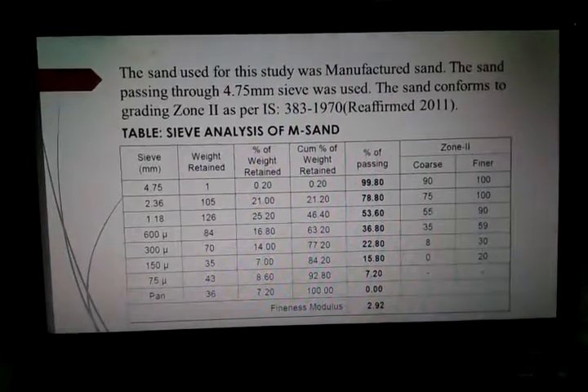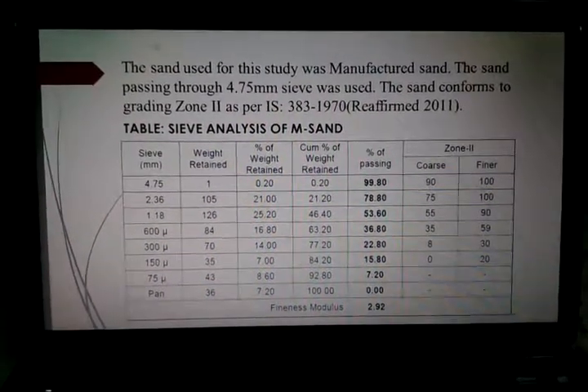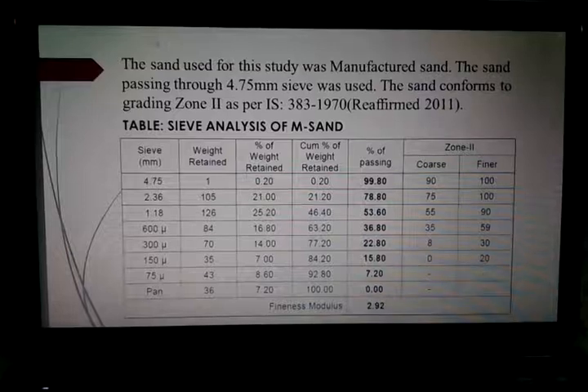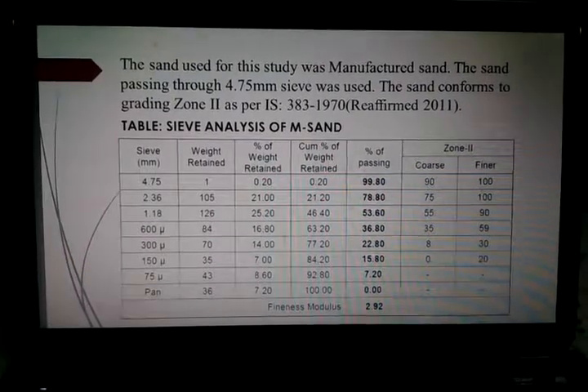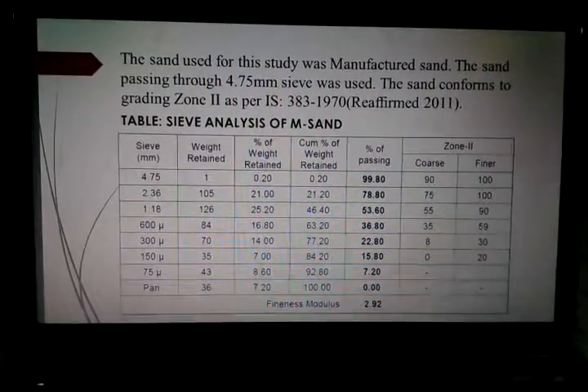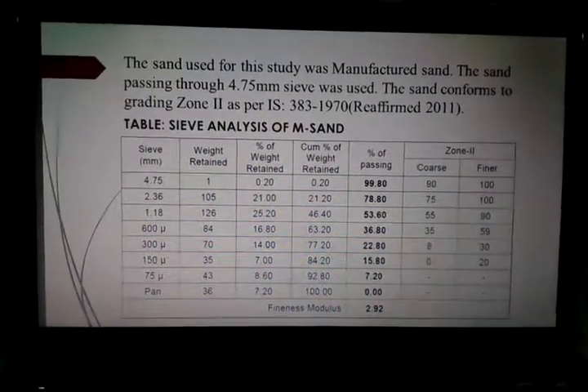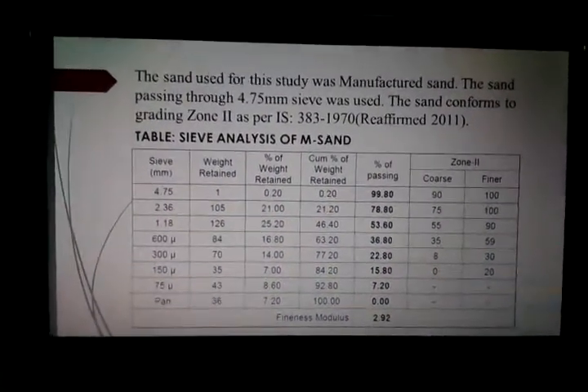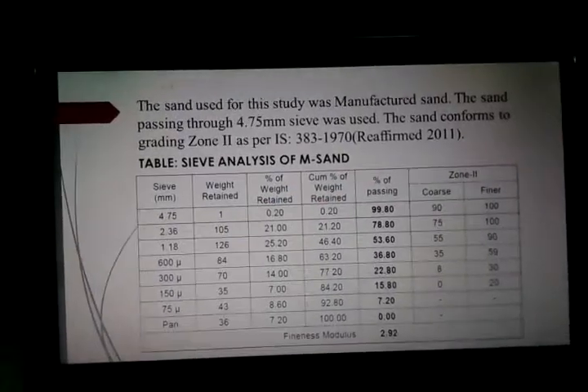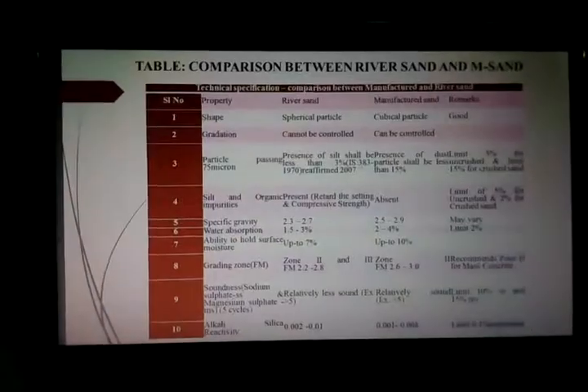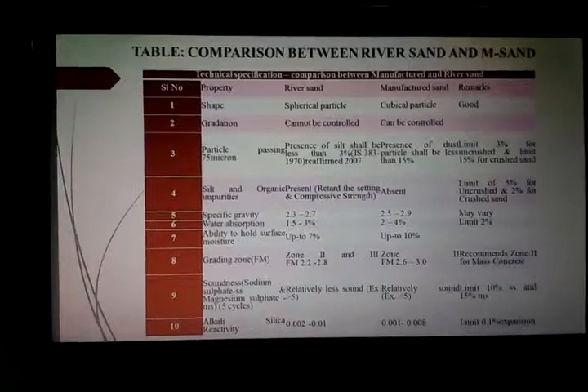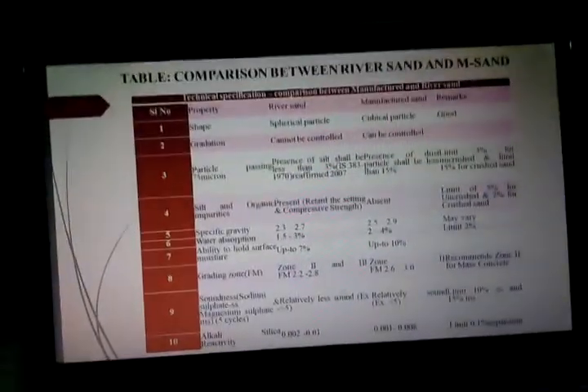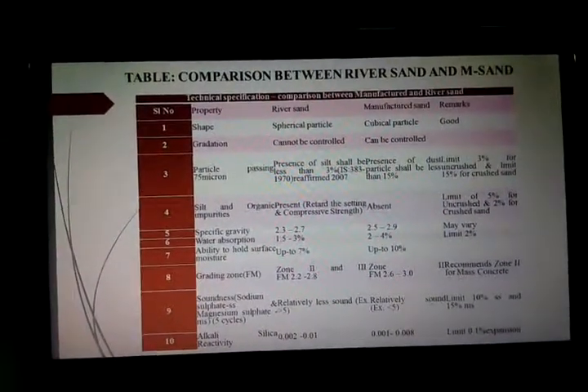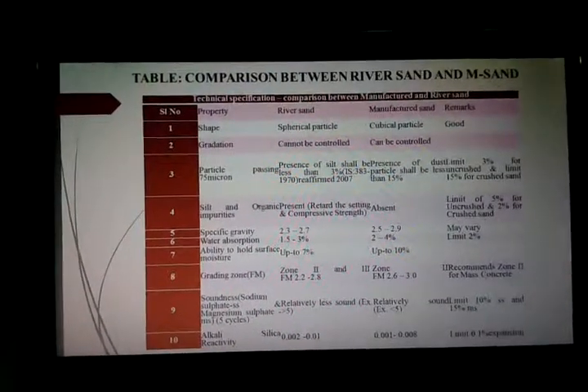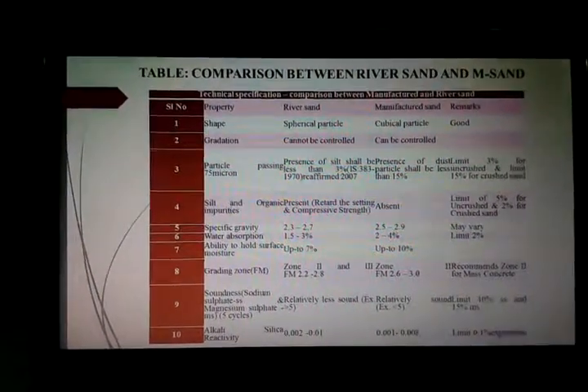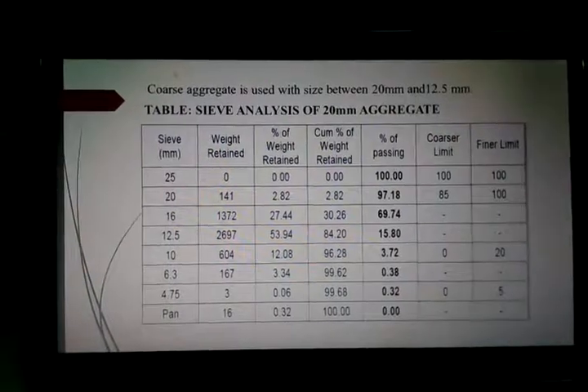The sand used for the study, as mentioned, is manufactured sand. The sand is passed through a 4.75 mm sieve. The sand conforms to grading zone 2 as per IS 383/1970, reaffirmed in the year 2011. The sieve analysis of the M sand is as given, and the fineness modulus of the same is 2.92. Comparison between river sand and M sand is as given. We have used M sand over river sand due to the following characteristics, and also because river sand availability is very minimal in the southern region of Tamil Nadu.